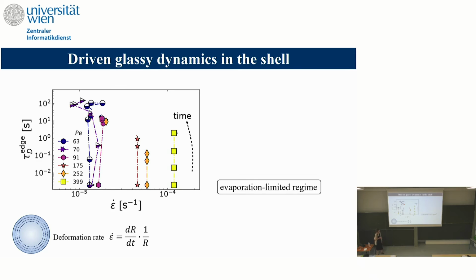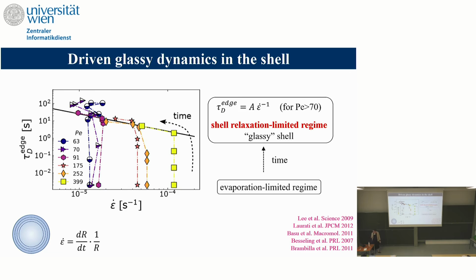It shrinks faster when it's drier, and it's the same whatever my Peclet number. So it's a regime where everything is governed by the evaporation, the relative humidity. Then sometimes you end up in another regime after a time, where you have your points, you see here, on this line, which has a slope, don't write it, of -1. This is another regime.